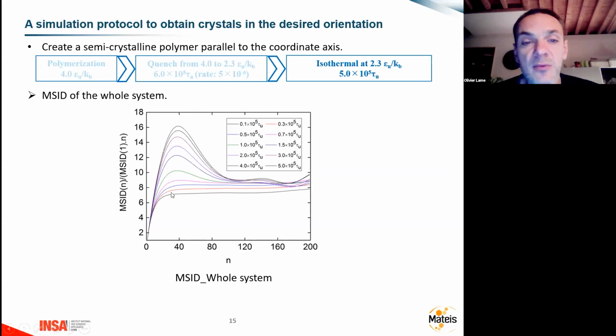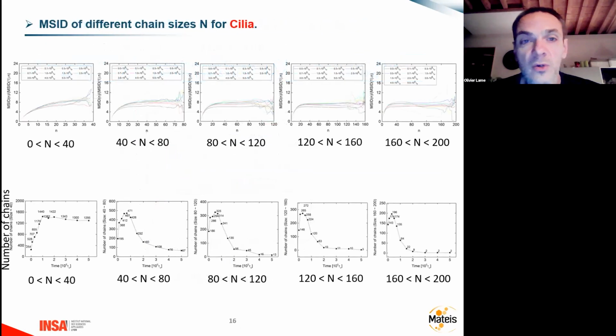And when we crystallize the system, we see this big peak appearing, but it's just because the chains are aligning in the crystallite, and then the internal distance is increasing. So this is not the most important indicator, because it mixes both what is happening in the amorphous phase and what is happening in the crystallite. So we have performed the same kind of analysis, but for each kind of chain in the amorphous phase, which is the most important goal for this study. I mean, the aim is to understand what is happening to each kind of chain when we crystallize the material, with the idea to be able after to understand better the origin of the mechanical properties.